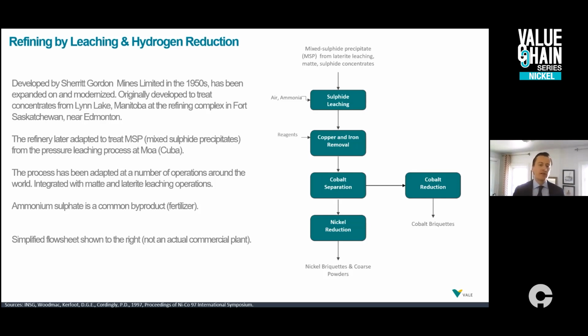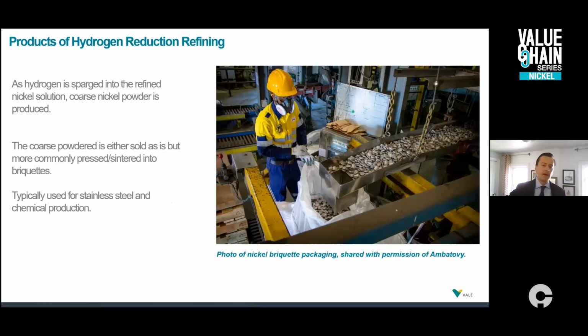This is several hundred microns in size versus, say, a fine nickel powder that would be under 10 microns in size. And most of the time, these powders are then compacted into a mold and pressed and/or sintered into what's called a briquette. It's typically a small almond-shaped piece of nickel. They do vary in purity depending on the refining process used to produce them. This is a photo that Ambatovy shared for us showing briquettes from their facility in Madagascar being packaged for production.